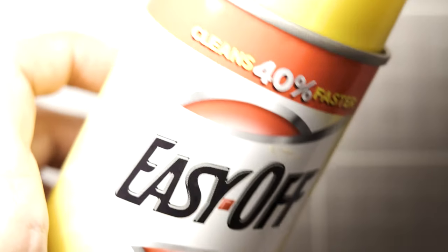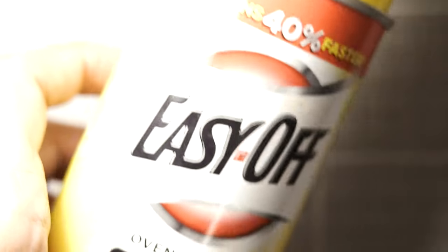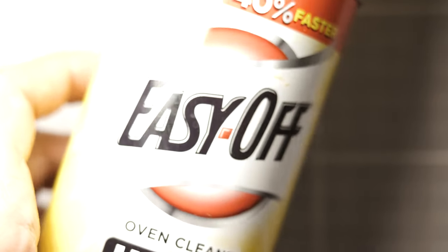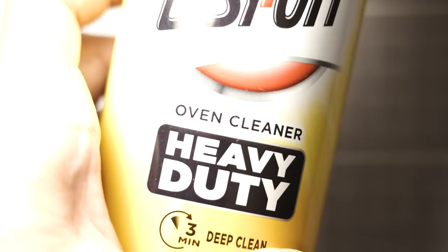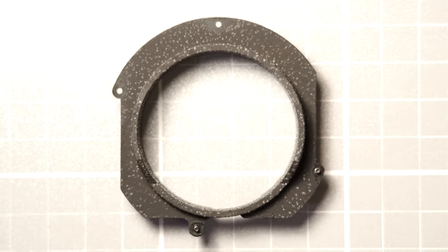To clean the rear cone, we're going to apply lye, which is found in Easy-Off Oven Cleaner. The reason we want to use lye is it can strip paint and oxidation without harming the plastic. Do not use acetone or other harsh solvents on the rear cone.